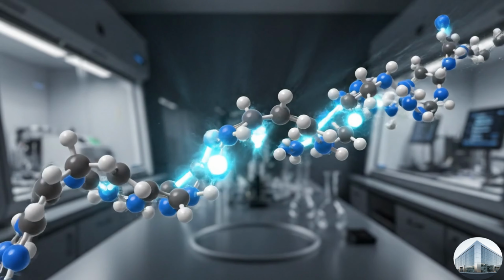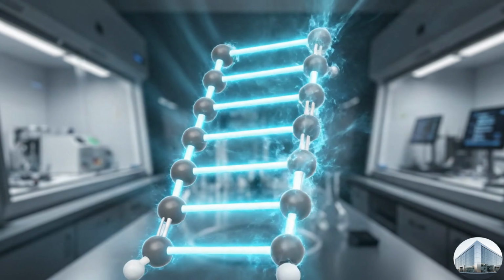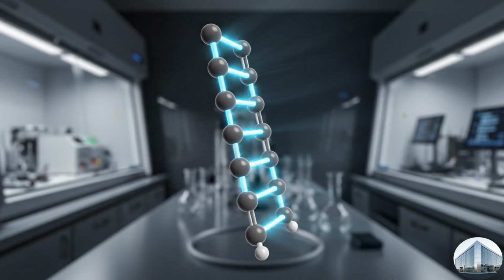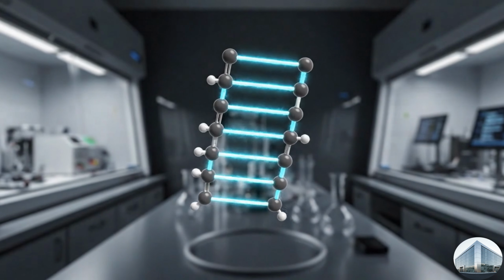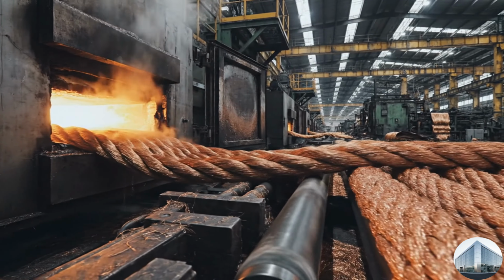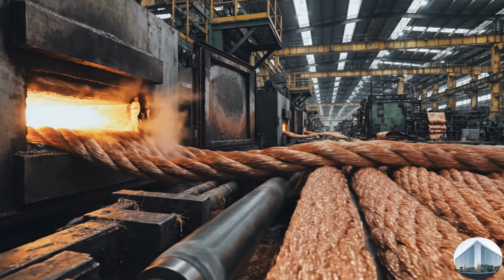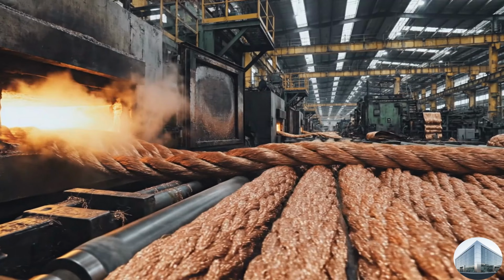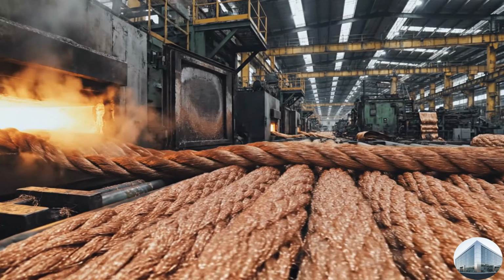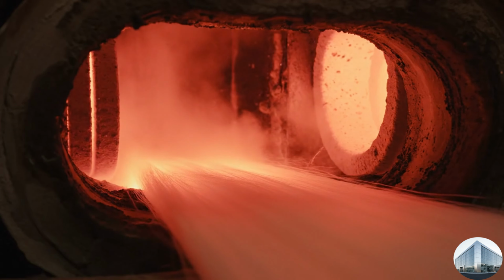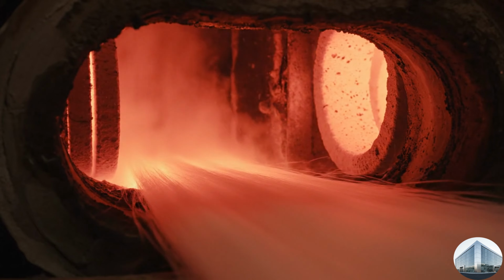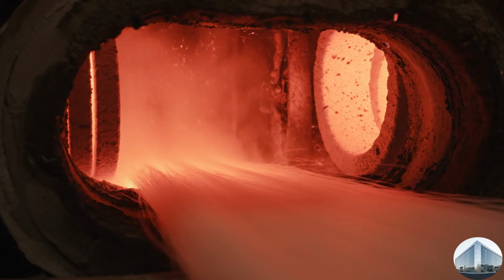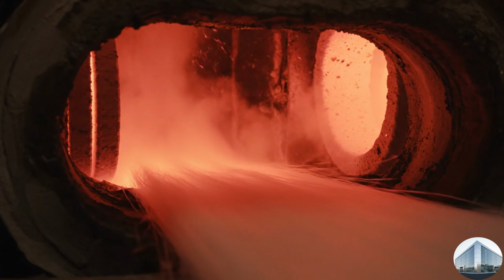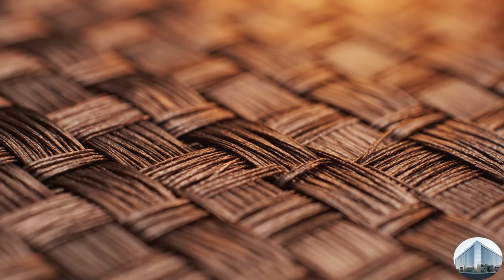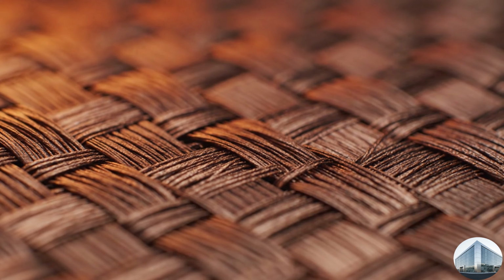The linear polymer chains start to close into stable rings, creating a ladder-like structure that provides the foundation for heat resistance. The transformation is visible to the naked eye. What started as soft white plastic has become a bronze-colored precursor, now capable of withstanding much higher temperatures in the next stage. The heat is relentless but calculated. Every strand must be baked evenly to ensure that the chemical conversion is consistent across the entire width of the fiber sheet.